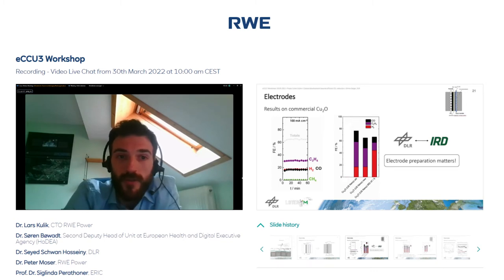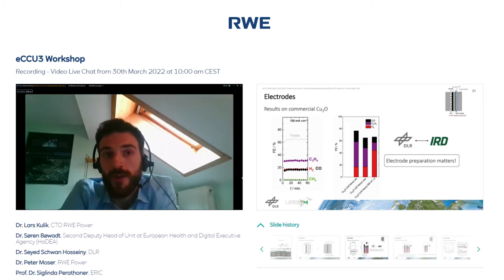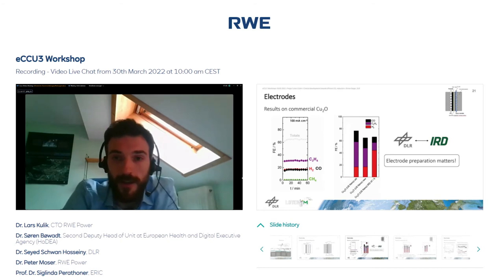And on the left side, you can see our small test protocol of 60 minutes at 100 milliampere per square centimeter to characterize different electrodes that have been manufactured. And this has been done now together with IRD, who are responsible within the project for large scale production of the electrodes. And the first result that we show here is that electrode preparation matters, because identical catalyst leads to different results. Like here, the right bar produced by IRD showed in the beginning quite high hydrogen evolution reaction. And we needed to first solve this by exchanging the recipe and really care about details.